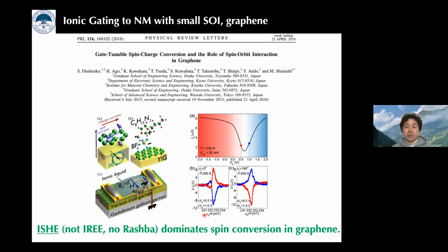Of course, my group has been using this very promising way to control physical quantities, and this is one example. In that work, we controlled the spin conversion in single-layer graphene using ionic gating. Here I show the device structure: single-layer graphene is transferred on top of yttrium iron garnet, a ferromagnetic insulator, and ionic liquid is placed on top of the single-layer graphene. Using the spin pumping technique, spin current is injected from YIG into the single-layer graphene. By applying gate voltages, we can control the carrier type in the graphene. As shown here, the red region is where holes are the dominant carriers, and the blue region is where electrons are the dominant carriers. As you know, electrons and holes have opposite polarity.